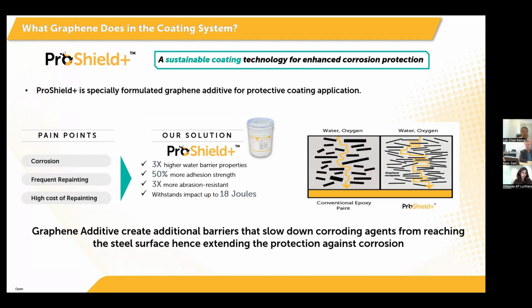Again, pain points. What we're really trying to address here is corrosion, effectively prolonging the effects of corrosion to the metal substrate, and with that, reducing the amount of repainting, which comes at a high cost. From the science angle, what we're really doing essentially is creating layers of resistance that slow down the permeation of water and oxygen to the metal substrate. So it creates additional barriers that slow down corroding agents from reaching the steel surface. And with that, we're able to extend by 2 times, if not 3 times, against corrosion.